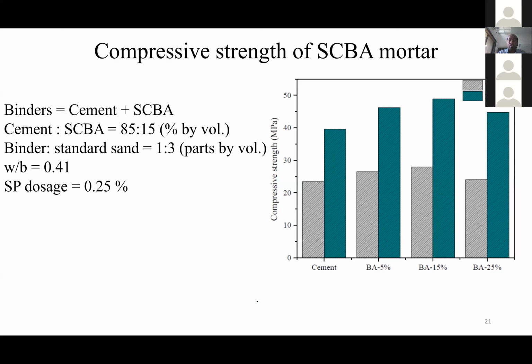You can look at the plot on the right hand side. With increase in bagasse percentage, the strength increases, and beyond that it is decreasing. Since the proportion of sand is constant, water cement ratio is constant, SP dosage is constant, the only factor which influences this particular increment in strength is the presence of SCBA, sugarcane bagasse ash. So we have seen that a systematic method of treatment process of SCBA into pozzolanic material plus a concept based approach for optimization of dosage will definitely give us a better strength.